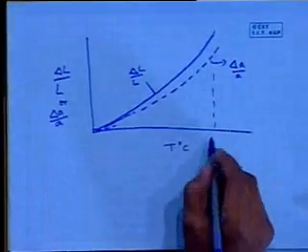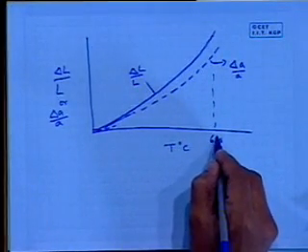And this increases as we get closer and closer to the melting point of aluminum, roughly 650 degrees centigrade. So the closer you get to the melting point, the more is the difference between the macroscopic measurement and the microscopic measurement from the XRD. Fundamentally, this is related to the formation of vacancies.